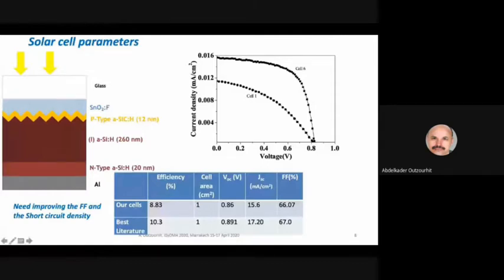It consists of an FTO-coated glass substrate, covered with a P-type layer of hydrogenated amorphous silicon carbide about 12 nanometers thick, followed by intrinsic hydrogenated amorphous silicon, 260 nanometers thick, and then an N-type hydrogenated amorphous silicon layer and the aluminum back reflector.